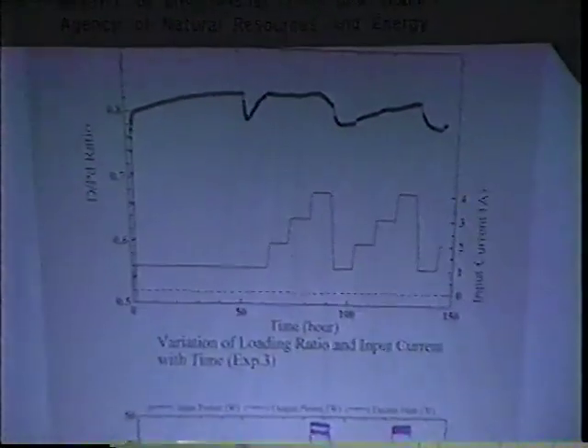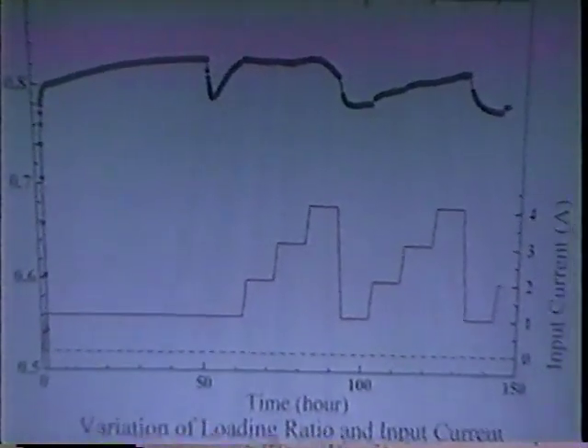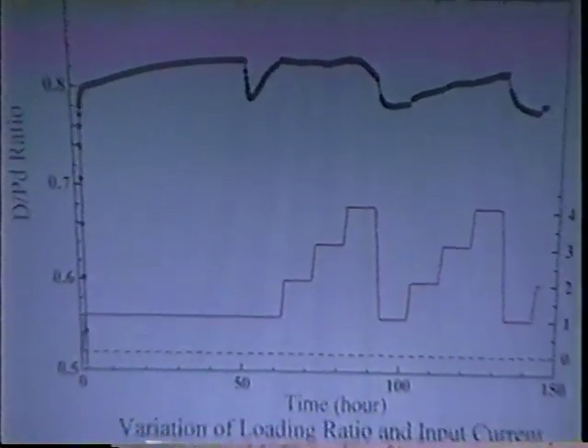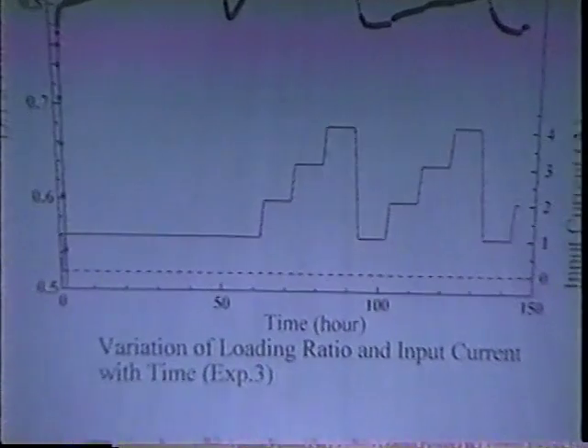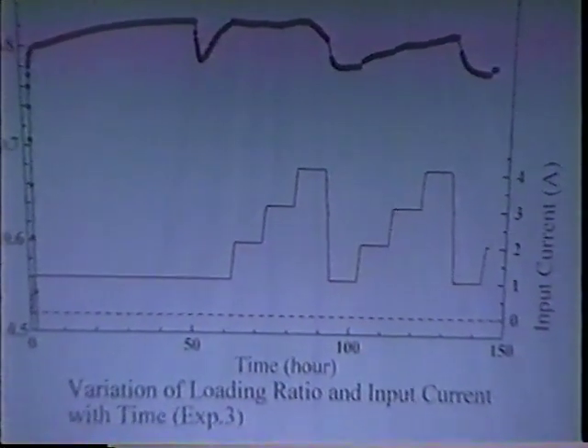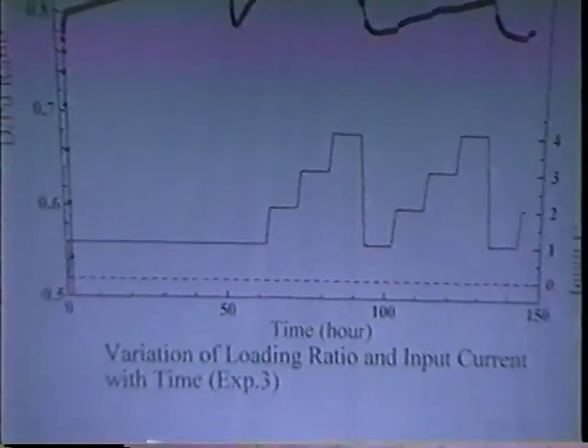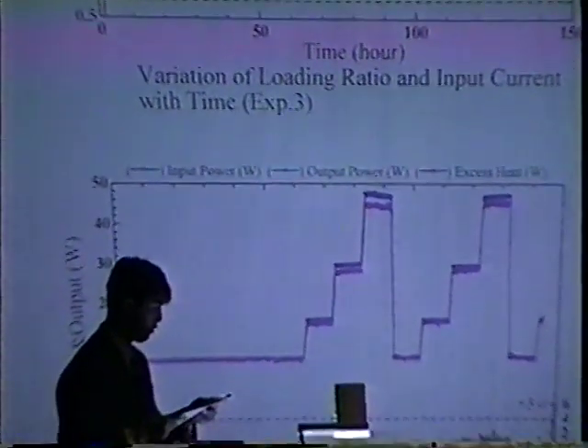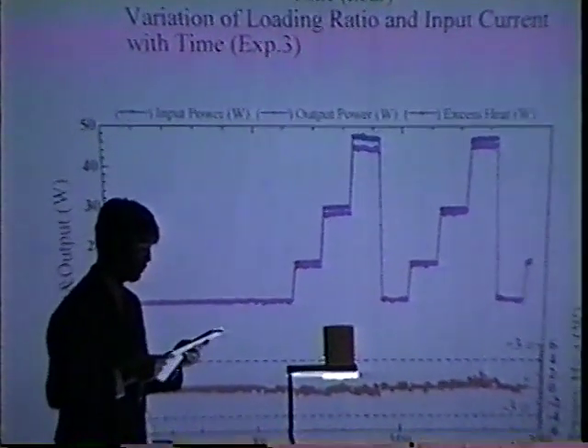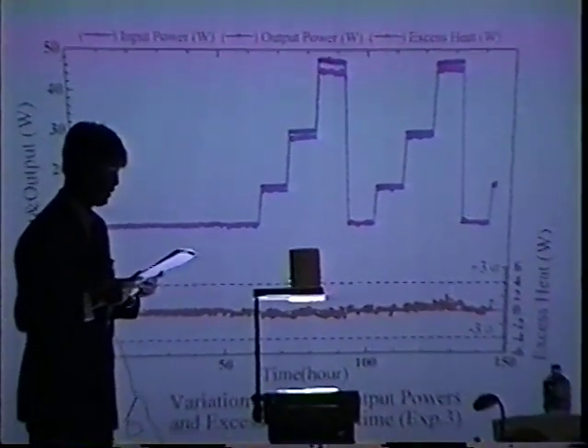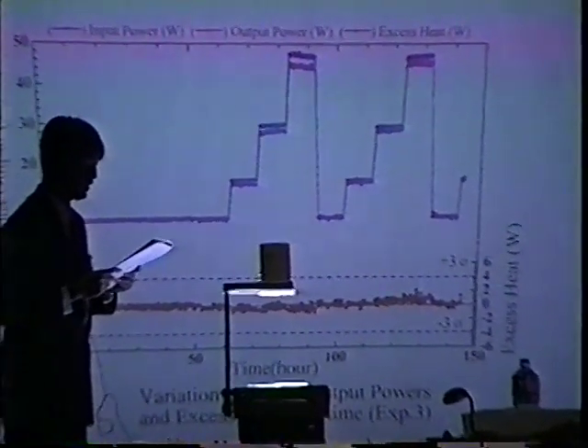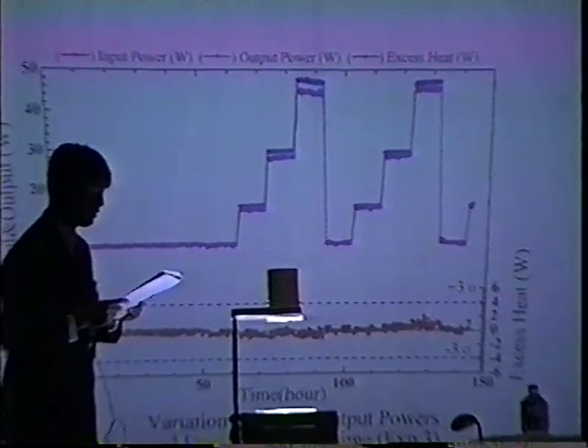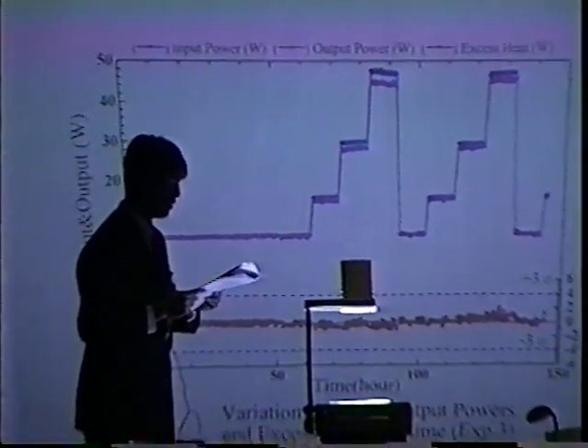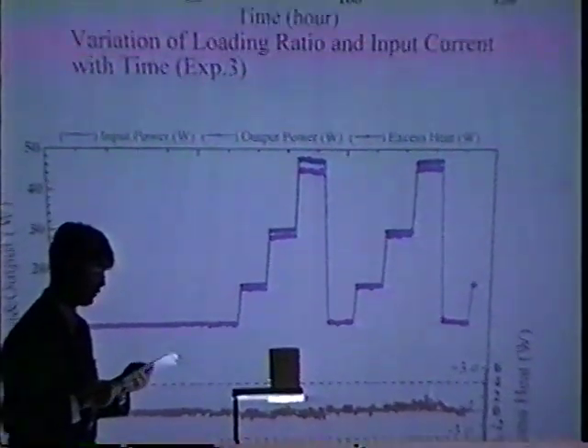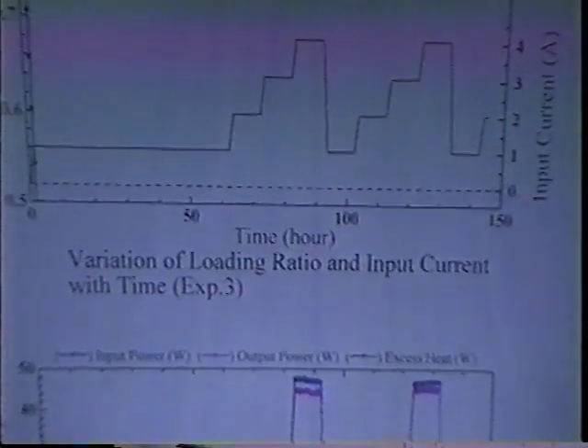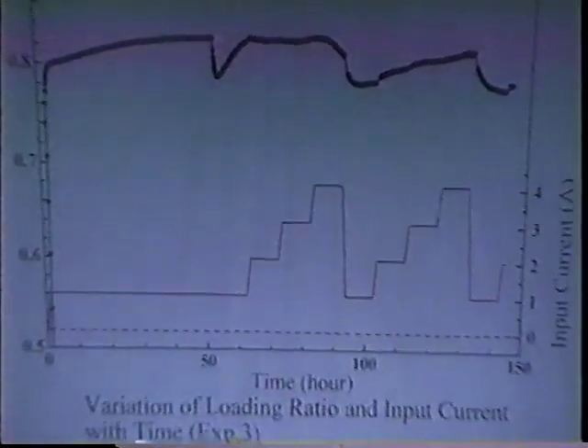This is the variation of excess heat and loading ratio as a function of time in experimental 3. In the run of experimental 3, between 120 hours and 140 hours after the start of electrolysis, excess heat looked like it was coming out. However, it was within the 3 sigma level of 99% confidence. 3 sigma equals 3.9 watts. Whenever anomalous excess heat was not produced, the heat balance was at the zero line, as in this figure, except for the 120 to 140 hours interval.